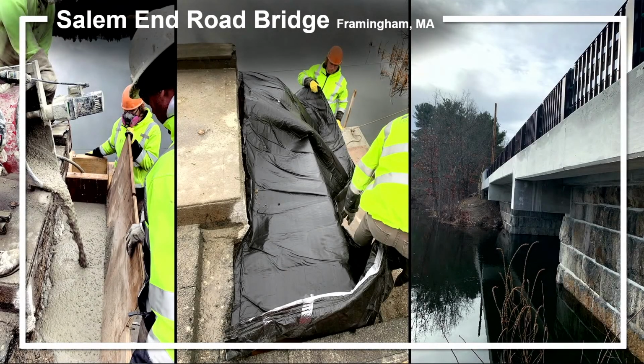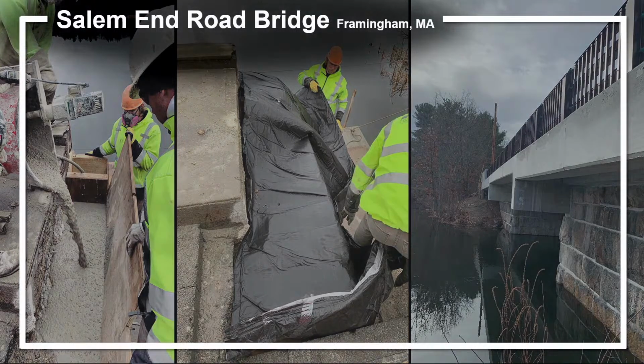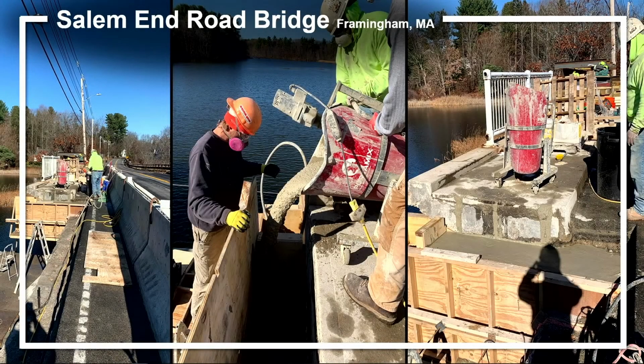And the last project here is the Salem End Road Bridge. This bridge was originally built in 1870 and was in desperate need of repairs. So they chose the DOT concrete mix. And the challenge on this project is they had very high temperatures and very low temperatures on the same project. So when it was very hot, they used cold water, and they used our Rapidset set control to give it extra working time. And when it was very cold, they used hot water and heated blankets to warm the substrate. Well, they got all the repairs in, and that's expected to extend the life of that bridge for another 20 years.